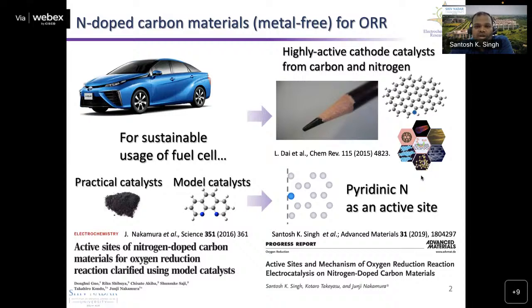But I can tell this is not the sole factor, that the presence of pyridinic nitrogen will bring the nitrogen carbon materials to higher activity. There are multiple factors that can regulate the higher activity of these nitrogen carbon materials. And we have concluded, as one perspective, that there is a very big role of hydrophobicity and wettability of the catalyst surface. So I'll be talking more about it in the next slides.